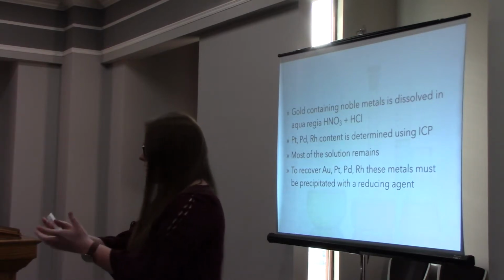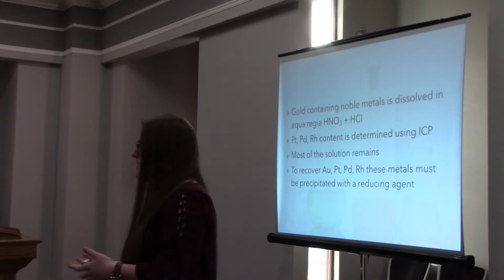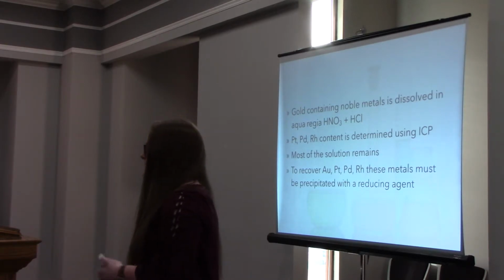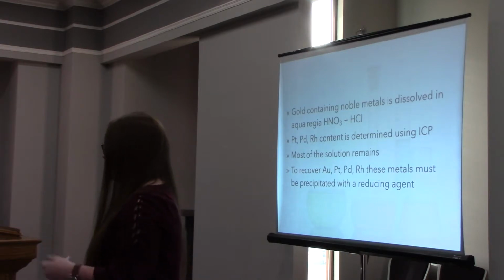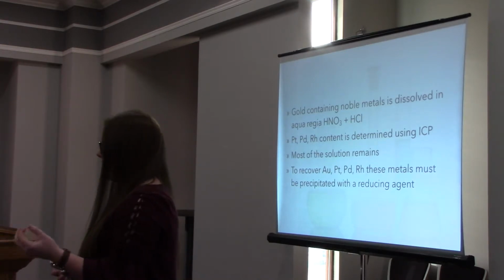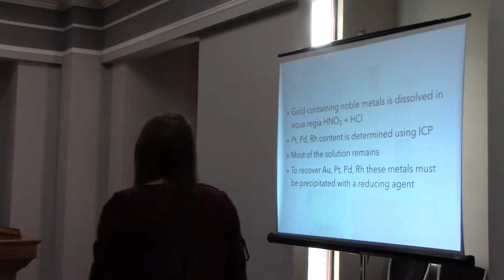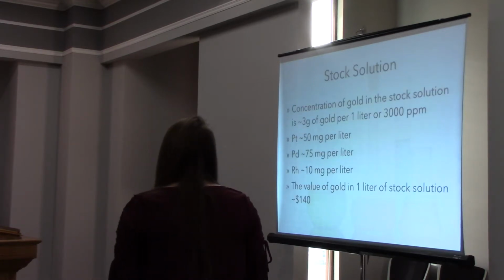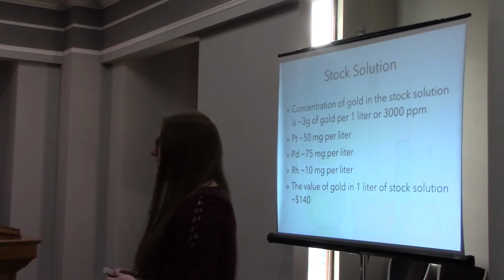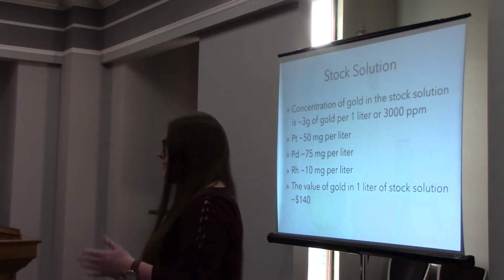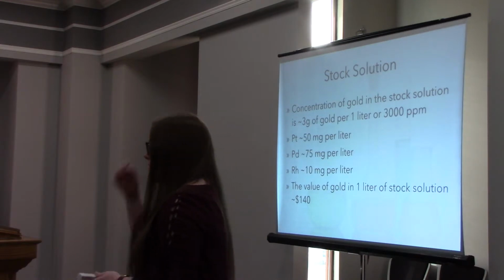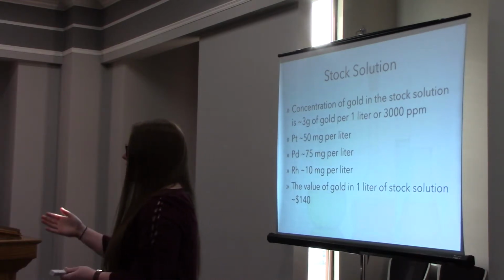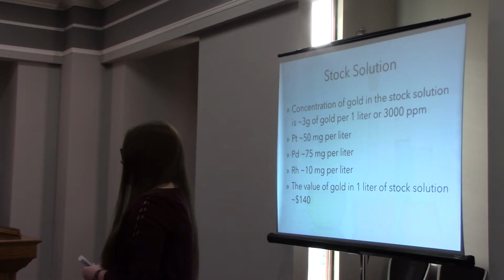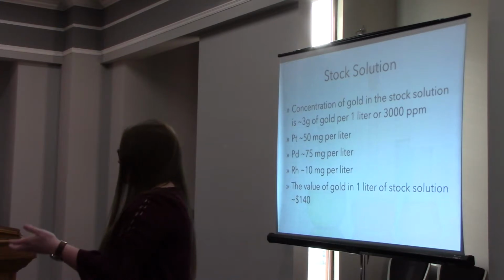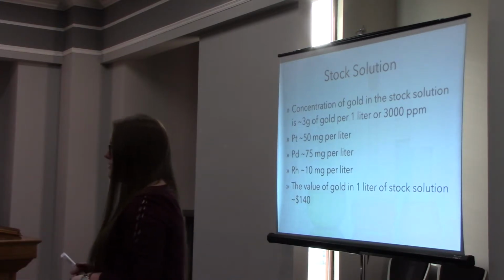But in order to recover it out of this liquid, because metals are hard, they're not liquid, how are you going to get the solid metal back out of it? You have to precipitate it out of the liquid with a reducing agent, which is the point of this talk. So you take the stock solution, and our stock solution had a concentration of about 3 grams of gold in 1 liter, and that's about what it normally is. The amount of gold is much higher than the platinum, palladium, and rhodium that's in it. And so in 1 liter of this solution, it's got about $140 worth of gold.